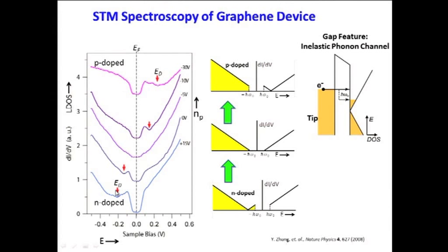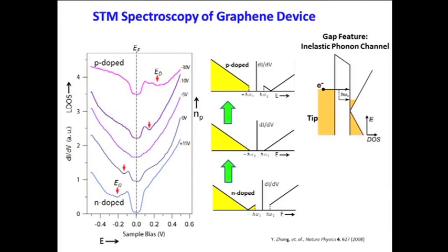The other little dip moves with gate voltage, which tells us it's a band structure feature — that is actually due to the Dirac point. You can see the Dirac point moving as you would expect as you p-dope the material. This is sort of the baseline STM spectroscopy of graphene, what we see after doing elaborate tip calibration procedures.